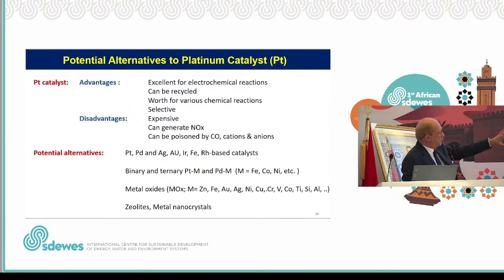The advantages of platinum is excellent for any electrochemical reaction. It can be recycled, it can be reused. It's worth for different chemical reaction. It's an excellent catalyst, but it's very selective, but it's very expensive. It can generate nitrogen oxides, which are not good for the environment, and it can be poisoned with different cations and anions and carbon monoxide.